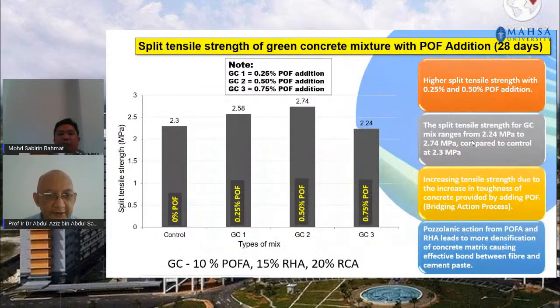Now, this is the split tensile strength of green concrete. The strength shows above the green concrete with zero fiber. Of course, when you add fiber, you are going to increase the tensile strength of the concrete. At 0.25%, the strength is about 2.58 as compared to 2.3. And for 0.5%, the strength is higher at 2.74 as compared to the other results. All in all, when we add fiber, obviously we are going to increase the tensile strength of the concrete mix.